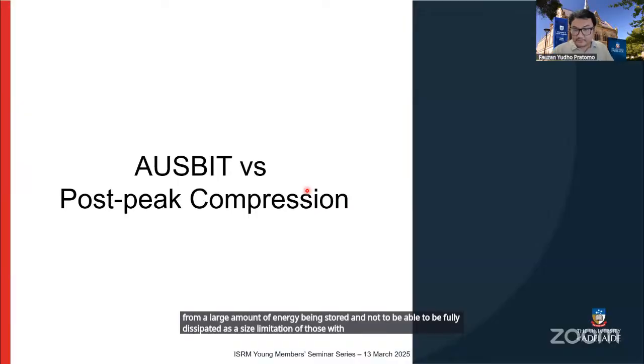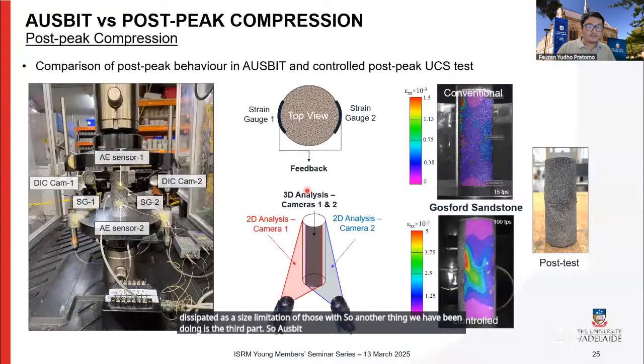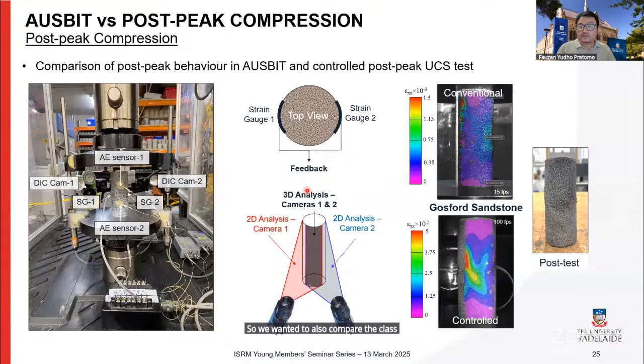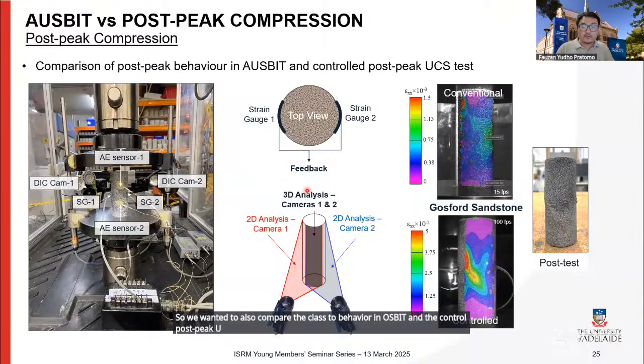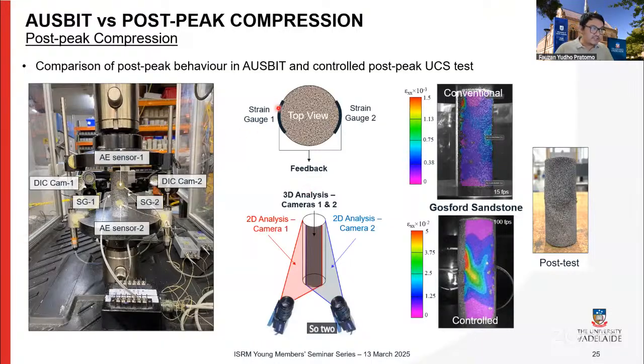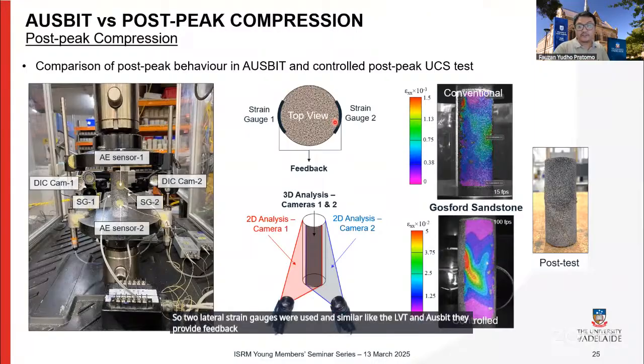So another thing we have been doing is the third part, AUSBIT and the post-peak compression. We wanted to also compare the class 2 behavior in AUSBIT and the controlled post-peak UCS test, to get an overview of the overall post-peak behavior under different stress conditions. Two lateral strain gauges were used, and similar to the LVDT in AUSBIT, they provide feedback into the loading system mechanism. And here we use 3D DIC compared to 2D in the AUSBIT, which allows us to analyze both in 3D and in 2D.